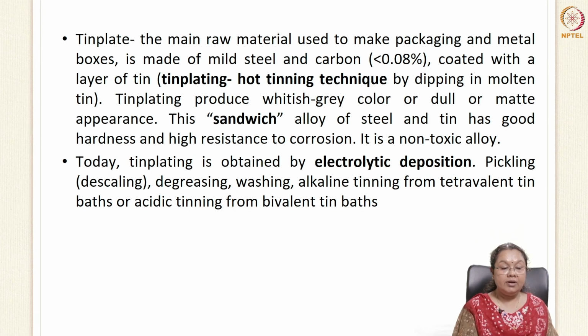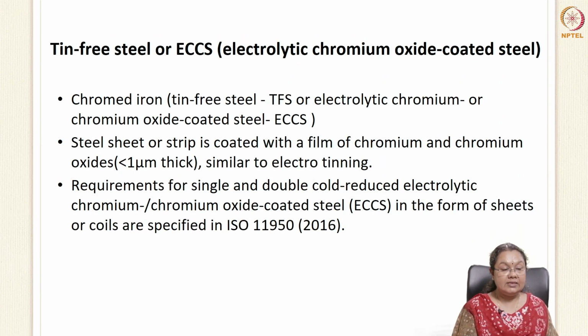Again, tin plating can be done by electrolytic deposition. It is another way of coating the tin, and this generally includes pickling, that is descaling, removing the unwanted parts and then smoothening, and then degreasing, washing, alkaline tinning and acidic tinning. Tin-free steel or ECCS, electrolytic chromium oxide coated steel. So this is a tin-free steel. It does not contain tin. Instead, it is coated with chromium, in the same way the electrolytic coating is given. So it can also be called chrome iron. It can be written as ECCS.